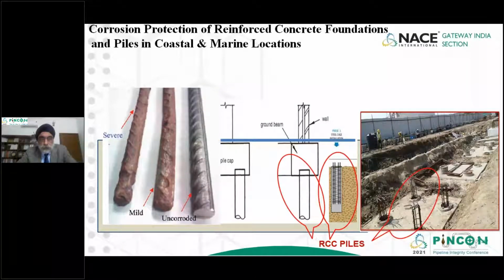If you see on the slide on the left-hand side, you can see steel rebars, one which is severely corroded, the other which is mildly corroded, and then there is a rebar which is not corroded. So the discussion today for the next 15-20 minutes would be to ensure that the rebar which provides the structural integrity to a concrete pile or a concrete foundation is maintained by ensuring that the rebar does not corrode with time. When the concrete structure or a pile is in ground, just like in the case of a pipeline, it is in contact with soil.